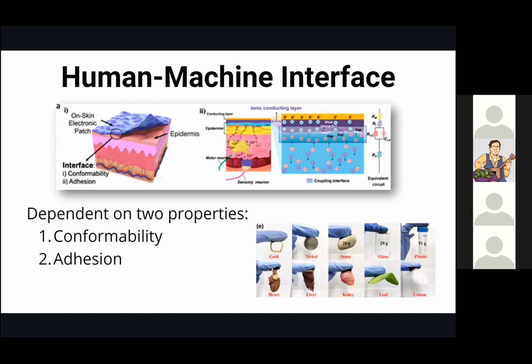In figure 2, we can see that low compliance creates gaps at the coupling interface, resulting in higher interfacial impedance. So the weaker the capacitive coupling of electronic and ionic current, the more noise or less sensitive and selective the device. So ideally, compliance is high and interfacial impedance is therefore low, allowing ionic fluxes to transduce efficiently across the skin barrier. So as we've seen, prolonged intimate contact with the dermal layer is difficult to maintain due to its stretchable and hydrophobic nature, as well as frequent dynamic deformation.